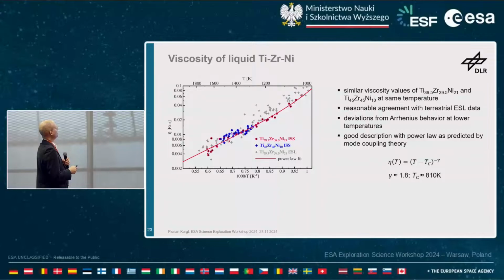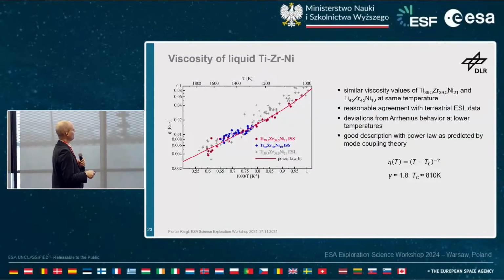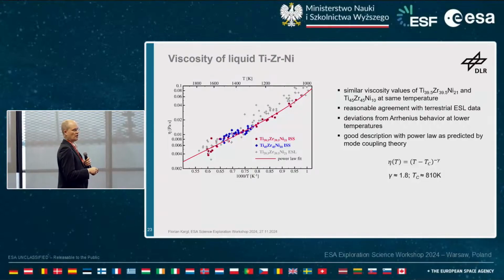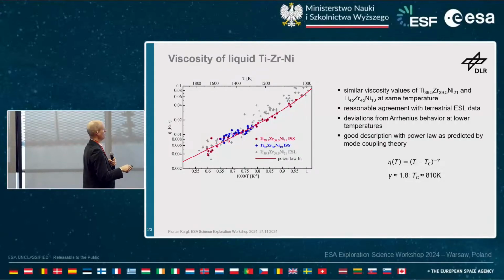So a second point of interest for these liquids is thermophysical properties, particularly here the viscosity measurement of the titanium, zirconium, nickel alloy with two different compositions. This has been done on the ISS for nickel 21, nickel 10, and for the nickel 21 also in electrostatic levitation on ground. Data is shown here in an Arrhenius plot. So you have logarithmic scale for the viscosity. You have an inverse temperature here. If it's Arrhenius behavior, it should be a straight line. So you clearly see a deviation here if you go to lower temperatures. And in particular for the nickel 21, it was possible to really deeply undercool the sample here.